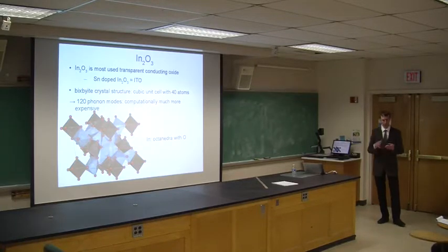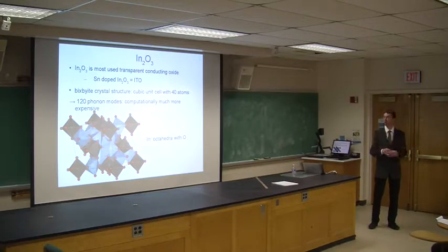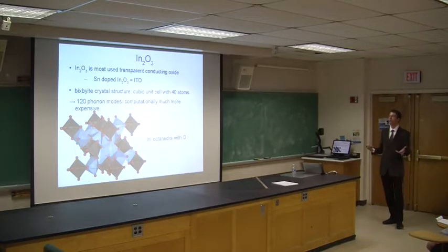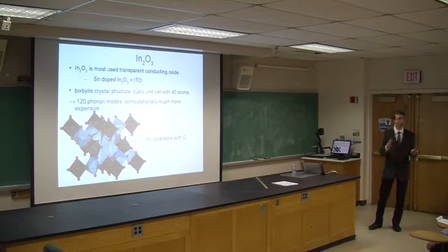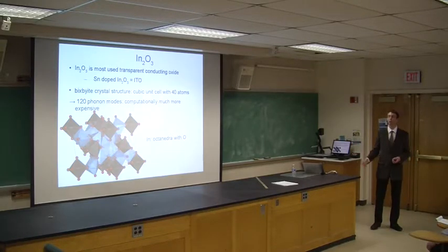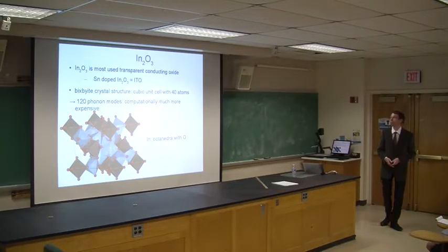The unit cell of this material is much more complicated compared to the tin oxide unit cell. It has the so-called bixbyite structure, where your indium atoms are in the center of distorted octahedra, and in your whole unit cell you will have 40 atoms. It also means you have 120 different phonon modes, which first of all increases the computational cost significantly, but also makes it much more difficult to really distinguish contributions of specific phonon modes.